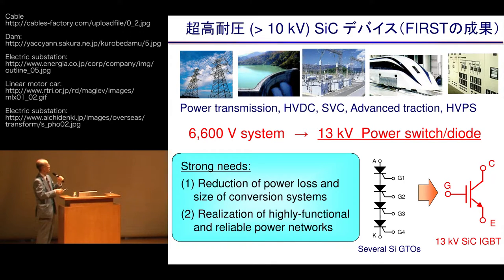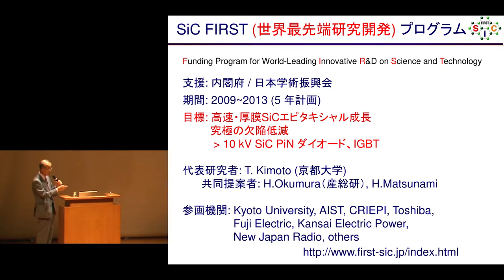And in Japan, power is transmitted at 6,600 volts. And so now in DC, the target would be to create a device at 13 kilovolts. If this is achieved, we need 4 units for silicon, but in the case of silicon carbide, we can replace them with only one unit. If there are 4 units, there is a high possibility of breakdown. From 2009 to 2013, our project was adopted in the first program. Our target was to come up with fast and thick silicon carbide epitaxy and defect reduction.